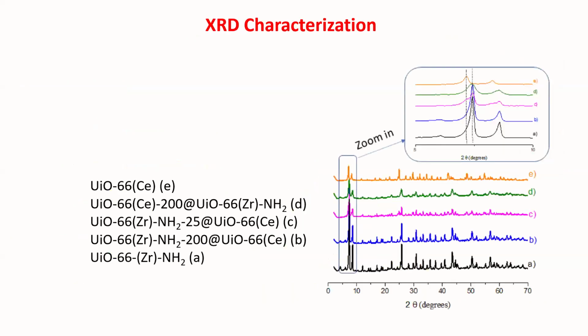This is a powder XRD which clearly shows the existence of the core peaks for UiO-66 zirconium and the cerium, and this is the expanded version. You can see that these are the peaks corresponding to UiO zirconium, and this is corresponding to the cerium. Since there is a slight difference in the ionic size of zirconium 4+ and cerium 4+, there are slight shifts in the peaks, but otherwise they are crystalline and correspond to the respective materials.